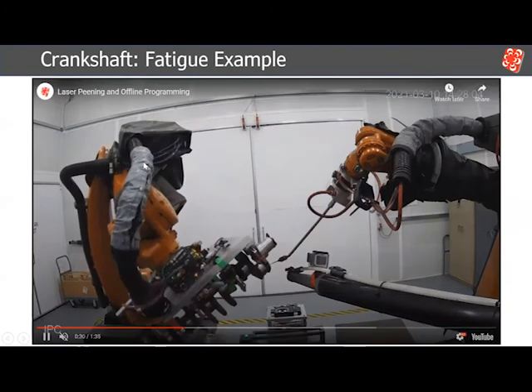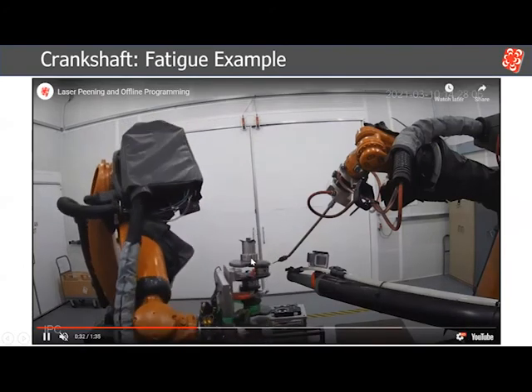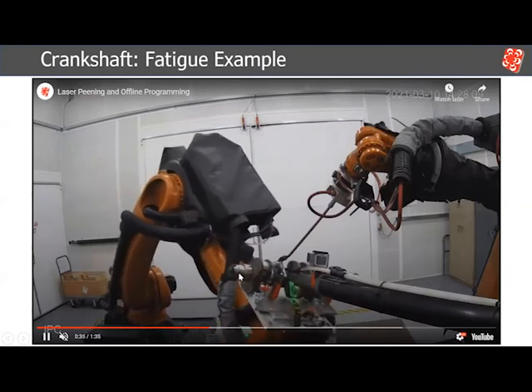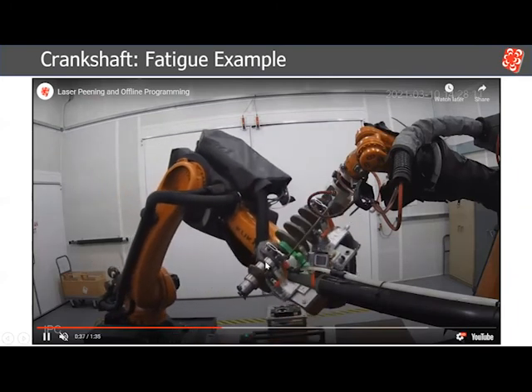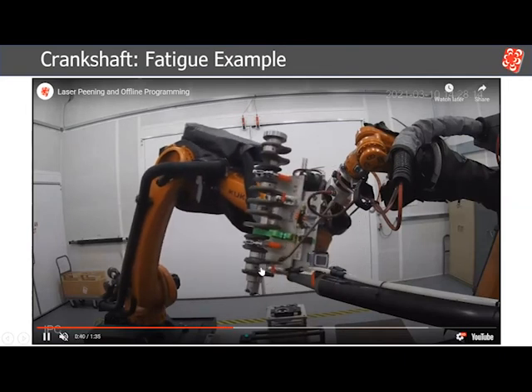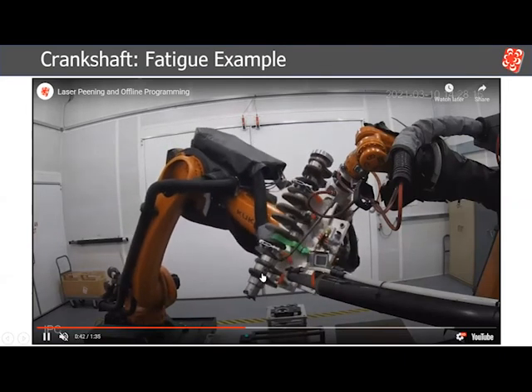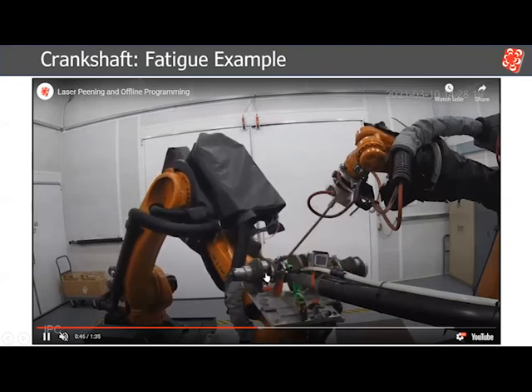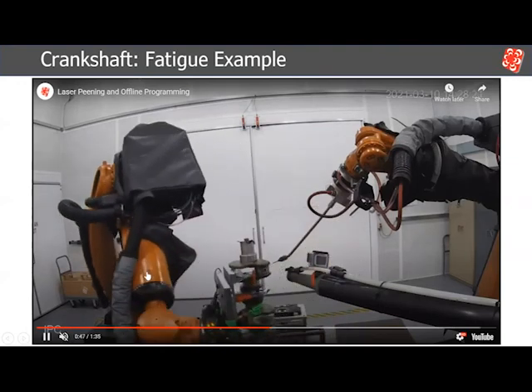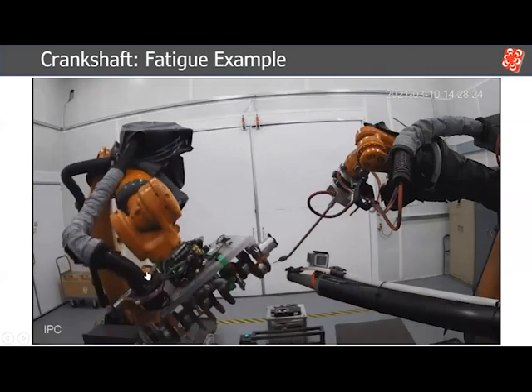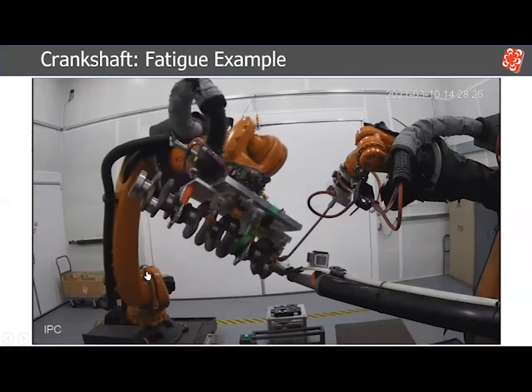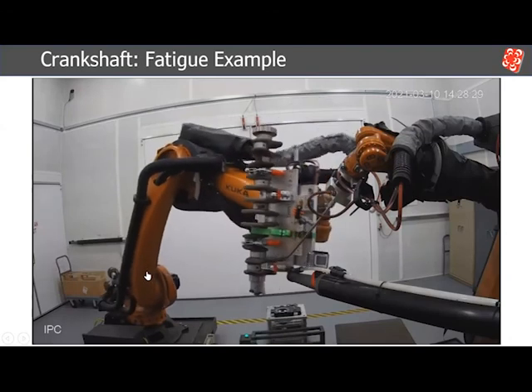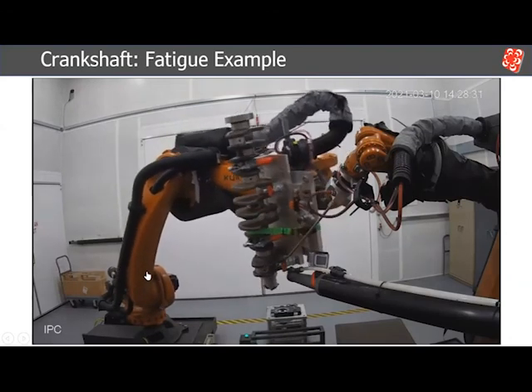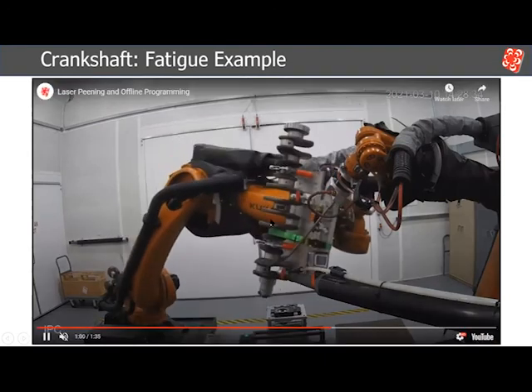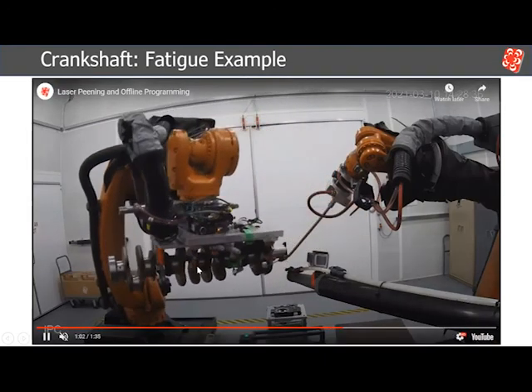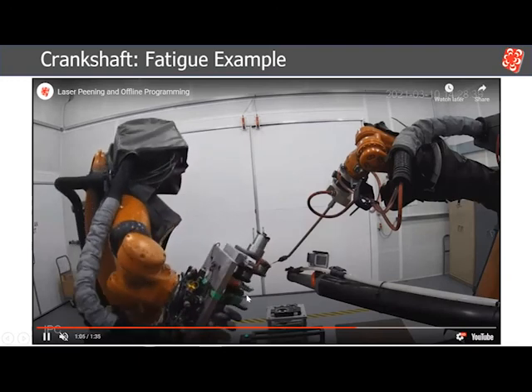Here in this application, we're looking at a crankshaft. Crankshafts have both. You have holes in them for the oil, and you also have fillets between the different features. In this specific video, you can see that we're laser peening the hole feature. In order to improve the fatigue life of the components, you need to laser peen and improve the life of the most critical areas, the areas with the highest stress factors. And in this example, it's a combination of laser peening the fillets and laser peening the holes.